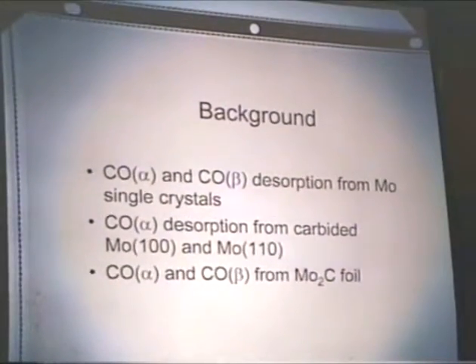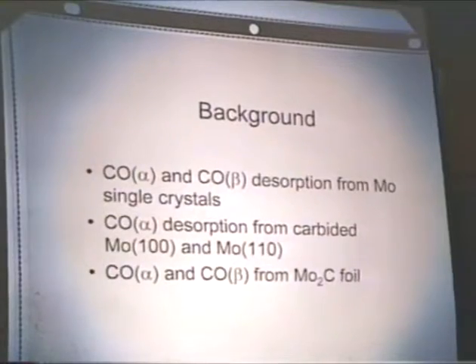Just as a quick background on CO work that's been done previously on moly single crystals. There are two known types of CO that desorb from a moly single crystal. These are denoted alpha and beta. CO alpha is a molecularly adsorbed CO that comes off at a relatively lower temperature compared to the beta CO. And the beta CO is a dissociatively adsorbed CO that comes off at higher temperatures.